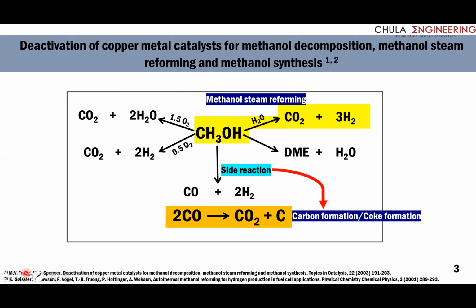In 2003, Twigg and Spencer studied the deactivation of copper metal catalysts for methanol steam reforming and methanol synthesis. Copper catalyst has very low activity for breaking the C-O bond or forming C-C bonds, and as a result, there is no formation of coke from any hydrocarbon that may be present. Nevertheless, although coke formation is essentially unknown in methanol synthesis, it has been observed in the reverse reaction, methanol steam reforming. The origin of this unexpected carbon formation has not been established, but there are several possible causes.